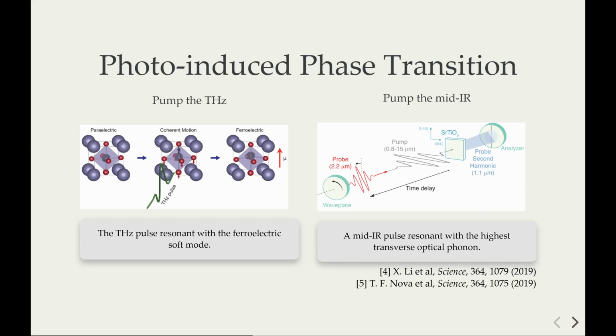Another approach found in 2019 is to perturb the system with a very strong electric field. Two independent experiments were done: one pumping the soft ferroelectric mode in the terahertz region, the other pumping the highest infrared active mode in the mid-IR region. Both show a spontaneous breaking of the inversion symmetry by measuring the transient second harmonic signal.